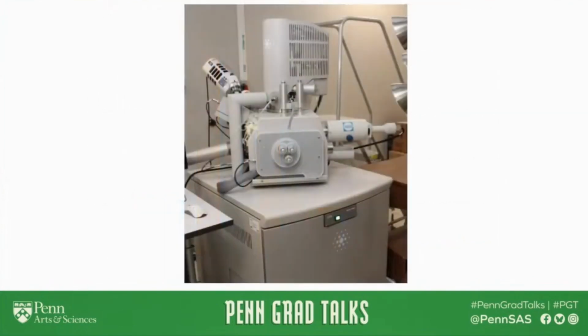Well, in order to figure this out, we had to start looking closer, and I mean literally. This means using instrumentation like this, known as an electron microscope, at the Singh Center for Nanotechnology here at Penn. We were able to use instruments like this to see our tire particles at microscopic levels and begin doing things like assigning elements to where we see the particles. Now, this is used a lot in material science, but for tire particles, it was a little new. And by pairing these tools with our image analysis method, we were able to develop a novel tire particle characterization way of actually seeing what's on our tire particles and why they have varying densities.